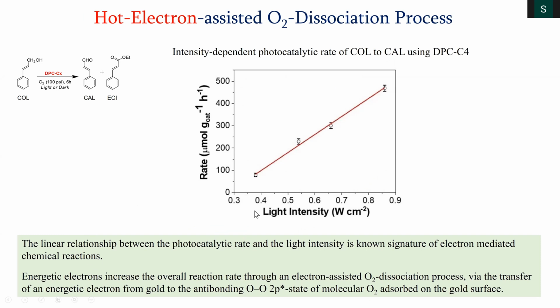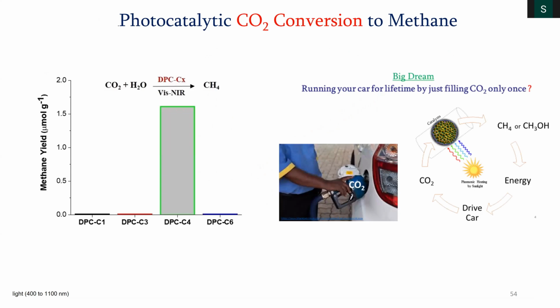We put more and more light, 0.4 watt per centimeter square, 0.5, 0.6, and you see the rate of a reaction increases in a superlinear fashion, indicating that yes, it is because of the hot electron transfer to the oxygen from the black gold. So that's a very unique mechanism that happens only in the plasmonic catalysis, not in other thermal catalysis.